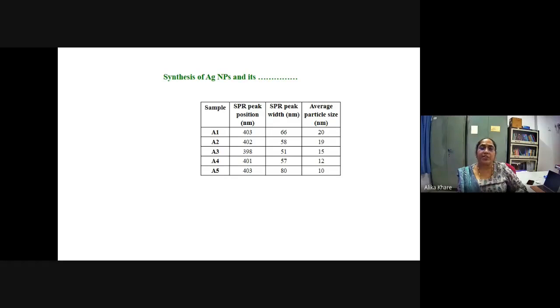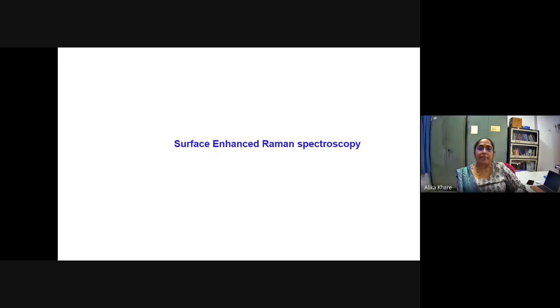This is the summary list of the SPR peak, FWHM, and size of the nanoparticle. In this case the SPR was not drastically affected, but one can see its FWHM getting affected, and the size is of course getting controlled by the laser condition.